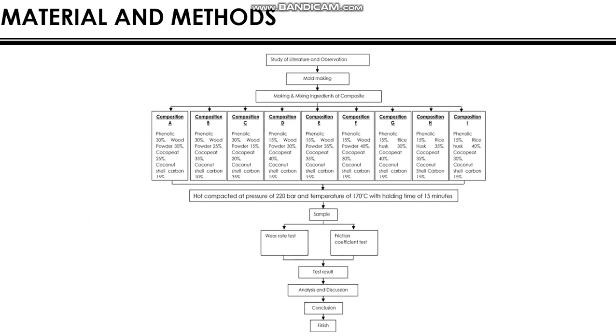Material and method. The first step is study literature and observation. And the next, mold making and the making and mixing of ingredients into 9 compositions. After making ingredients, the composite is hot compacted at a pressure of 220 bar and temperature of 170 degrees Celsius with a holding time of 15 minutes. After the sample is compacted, the sample is tested. The tests are the wear rate test and friction coefficient test. After the test results are obtained, they are analyzed and a conclusion is made.